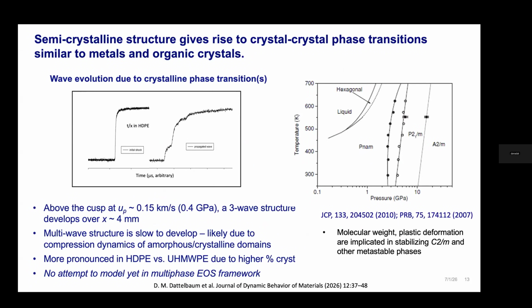The next thing I wanted to point out is, as we all work in high pressure science, we know that often there can be a lot of phase transitions at low pressures. And most polymers have pretty low symmetry structures as far as their initial crystalline structure, so they're often orthorhombic or monoclinic structures. And one of the things that we saw in our wave profiles with HDPE, the highly crystalline form of polyethylene, is that over time and distance, we actually saw that wave split into what looks to be a three-wave structure.